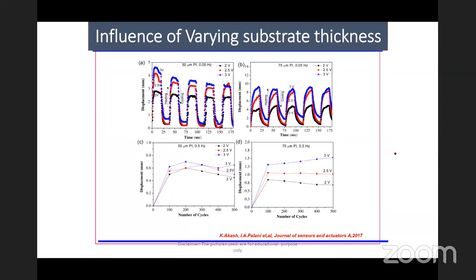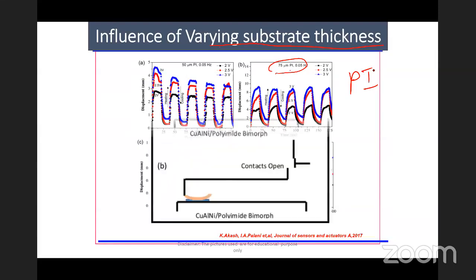In this life cycle analysis, we went for a continuous displacement. By changing the continuous displacement and going for alternate heating and cooling, we can go for a higher life cycle. In fact, our life cycle was basically relying on the substrate thickness. So we went for different substrate thicknesses, and we found that 75 micrometer polyimide was highly helpful for us to get a longer life.